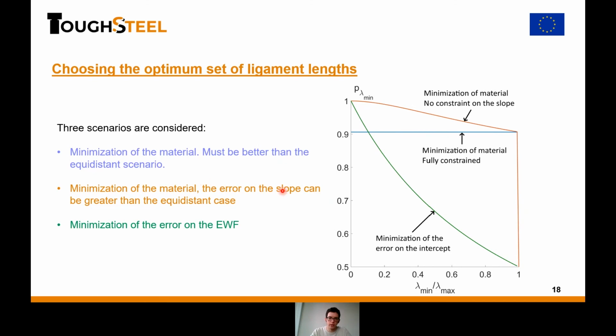Now, if I don't really care about the slope, I still want to minimize the material, and I still want to keep the error on the intercept, so the error on the essential work of fracture, smaller than this equidistant case. In this case, we have this orange curve, and we see that we even have a larger proportion of samples that has this lower ligament length, which sounds logical.